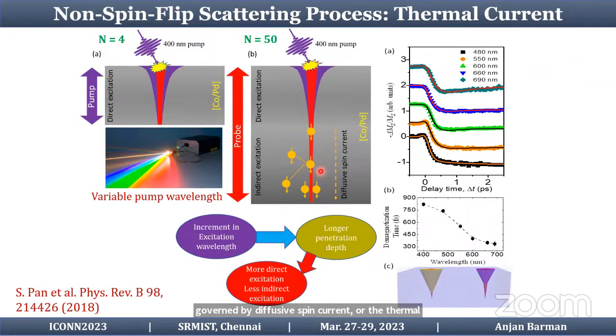In order to confirm whether our model is correct, we do a control experiment. We do pump probe spectroscopy, and instead of a simple 400 nanometer excitation, we vary the excitation wavelength. You can see the excitation wavelength here increases from 480 to 690. At 480, it is still type 1 and type 2. As we increase the wavelength of the pump beam, it slowly transforms into purely type 1 demagnetization, even for this sample. Basically, as we increase the pump wavelength, we go deeper and deeper into the sample, and we transform from direct and indirect excitation to primarily direct excitation. So we clearly show that both direct and indirect excitation can coexist, and they can be controlled by a simple experiment like changing the pump wavelength in this system.